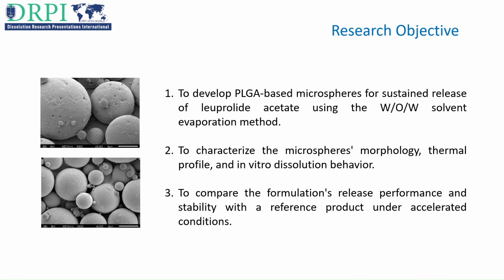The objectives of this research are to develop PLGA-based microspheres for sustained release of leuprolide acetate using the double emulsion solvent evaporation method, to characterize the microsphere's morphology, thermal profile, and in vitro dissolution behavior, and to compare the formulation's release performance and stability with a reference product under accelerated conditions.